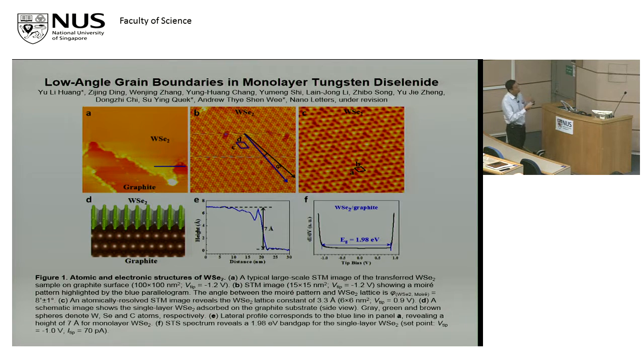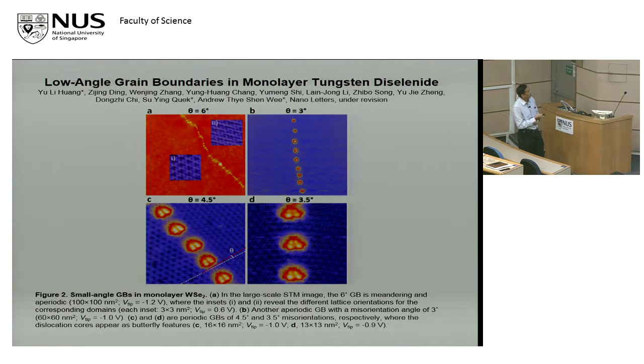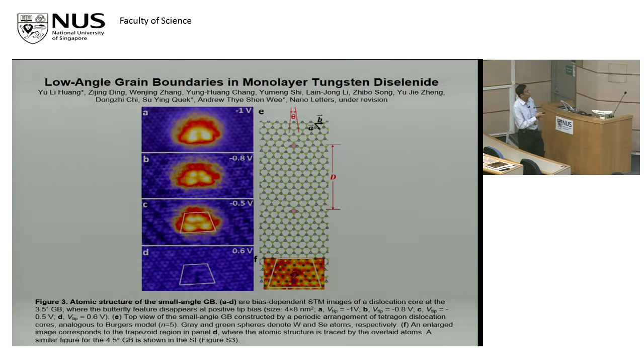Again, we see a very nice structure on the surface of the single layer. We can measure its band gap. And at grain boundaries here, we see very interesting core structures at these locations. These images are electronic, because if you change the bias, they can disappear at certain voltages. That's why I said in STM you are measuring an electronic image. So it's not some molecule on it. It's just the electronic patterns on the surface as you change the bias.